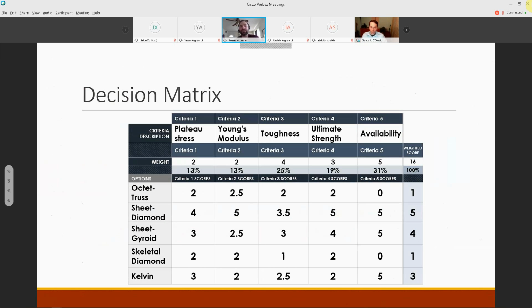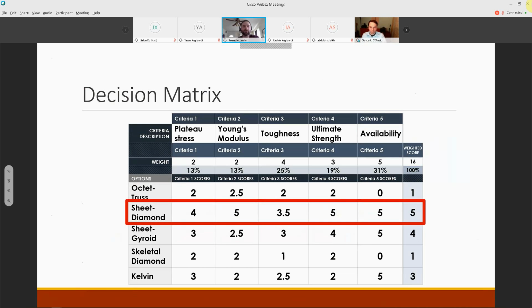So we did a decision matrix to decide which structure we wanted to use in order to move forward in our project. We took a couple of criteria based on what we had: plateau stress, Young's modulus, toughness, ultimate strength, and of course the availability of the lattice structure within the program we were using. A few of them that were stronger we weren't able to use, but the sheet diamond, in terms of across the board strengths and availability, we were able to use.